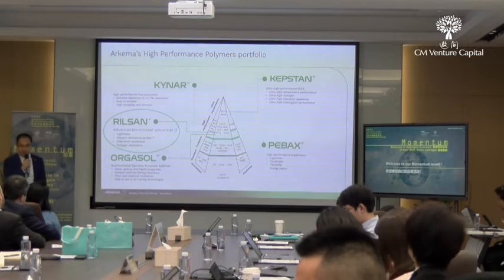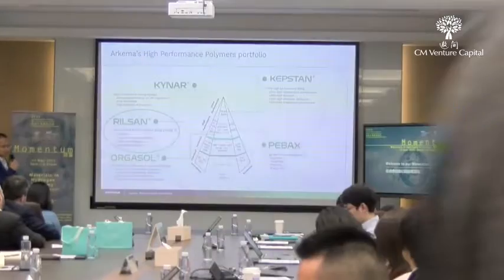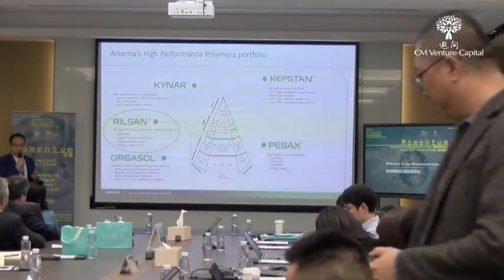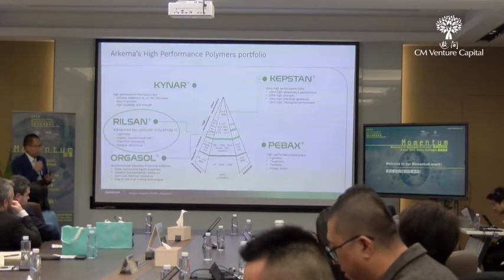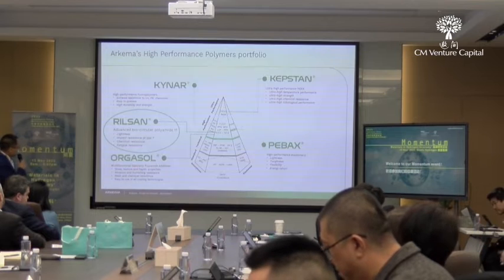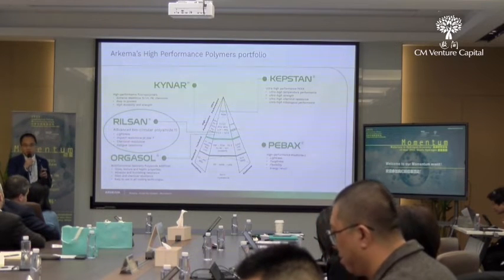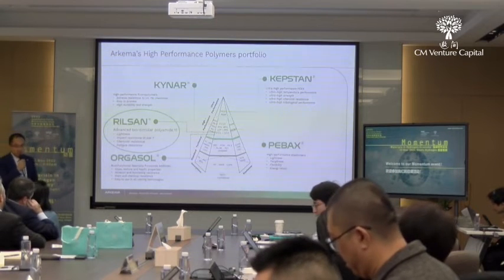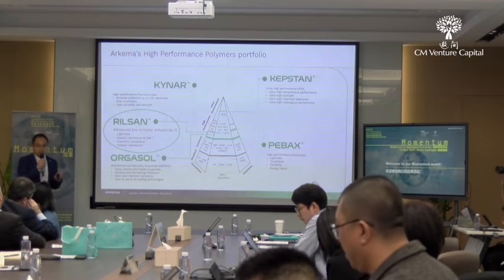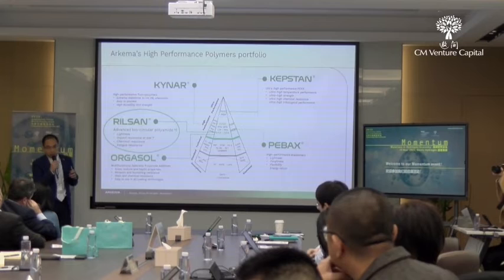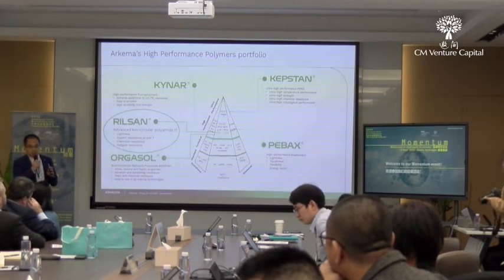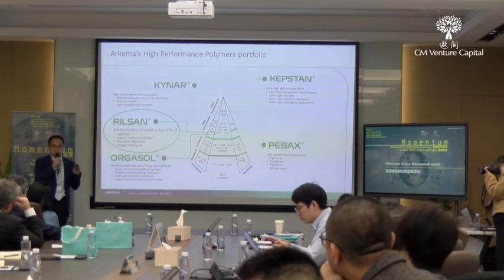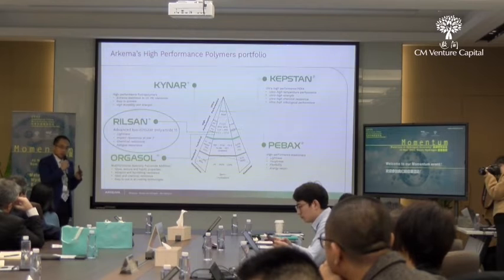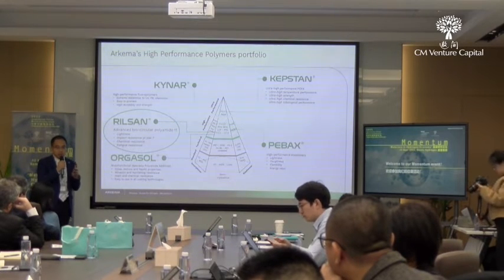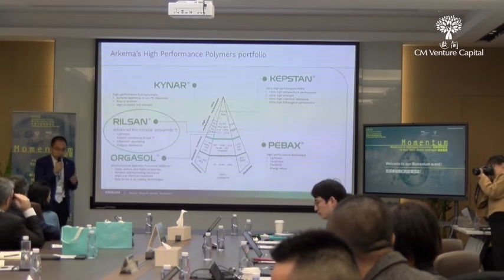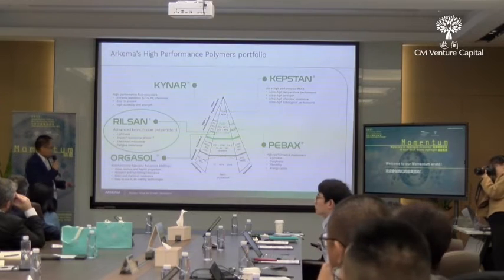And the rest is our polyamides, but we will highlight this one. The reason is PA11, which we chose for the Type 4 tank liners. Another one I want to mention is Rilsan fine powders, produced from PA11. It can be used as a coating solution for metal, both for Type 4 tanks and, as some colleagues mentioned before, as an inner coating for liquid ammonia, liquid methane or even liquid nitrogen. We have some new developments with these materials as well.